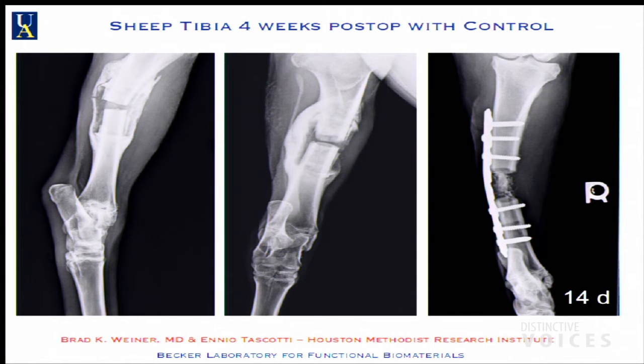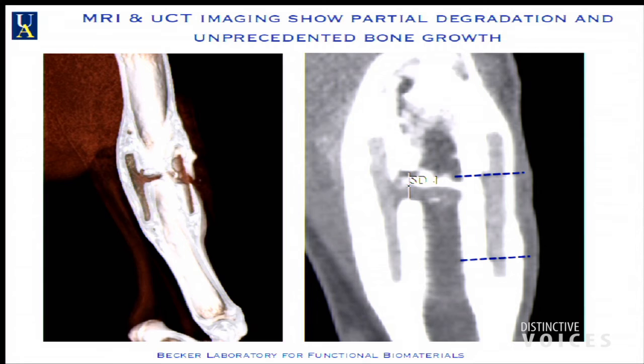Okay, and so at 14 days, this bends, they put the animal down. This was interesting in that on this particular side, which is where they did the incision, the sutures didn't hold, the membrane split. And the body's normal healing mechanism was able to compensate for that by growing significantly more bone around 180 degrees on that side relative to this side, so that sheep was still able to ambulate normally. Okay. Now this went 4 months. Actually, this was 4 weeks. At 4 months, it's a total structural heal.